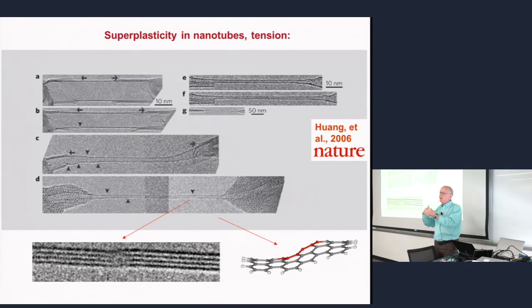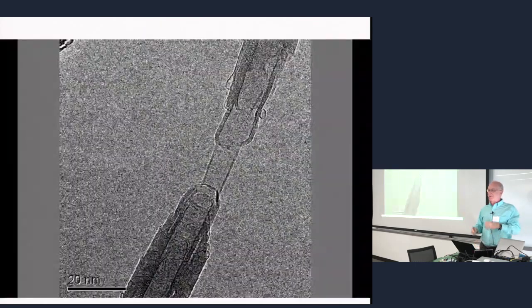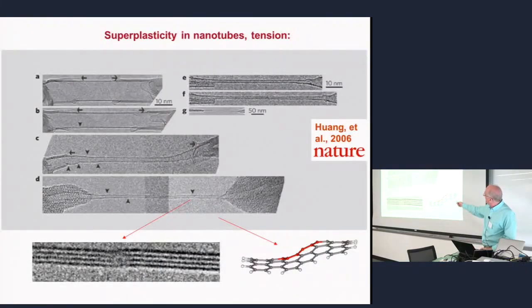They just drive current, like the lamp bulb. You don't have incandescent lamps here. But you heat it up to above 2000, very high temperature, and apply tension. And that's what they see. They see what they call superplasticity. They see that this structure elongates, it doesn't break. It elongates like 3 times. It becomes thinner, thinner, thinner. And if you look carefully, they also see little kinks.